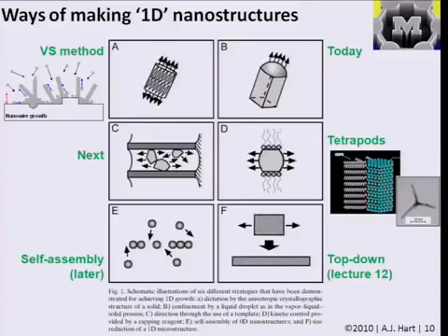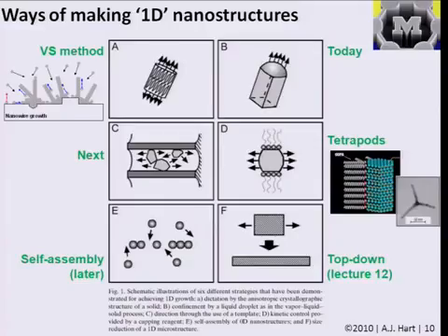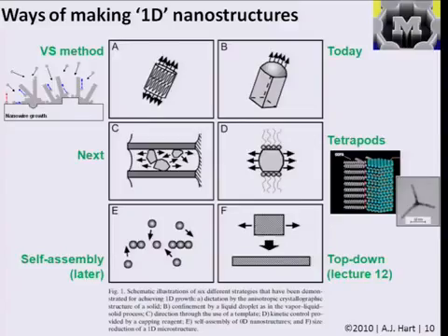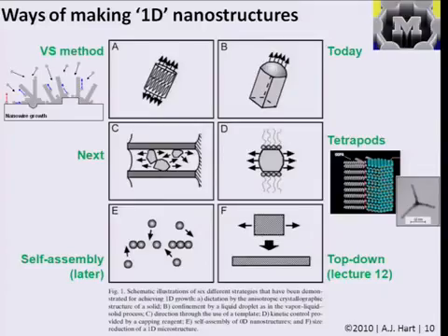We saw one example of this in the last lecture, where research from Berkeley grew cadmium selenide tetrapod structures by identifying a molecule that passivates a certain crystal surface, allowing control of arm growth — a lot of lengthening rather than fattening of the arms. Top-down methods were discussed in lecture 12 — higher-resolution lithography going to tens of nanometers can carve out wires and arrays of wires. However, remembering dimensional limits, we can't controllably approach single-nanometer dimensions, which is where a lot of controlled synthesis efforts for nanotubes and nanowires are focused. There are also issues with defects and wire orientation not addressed by top-down lithography.